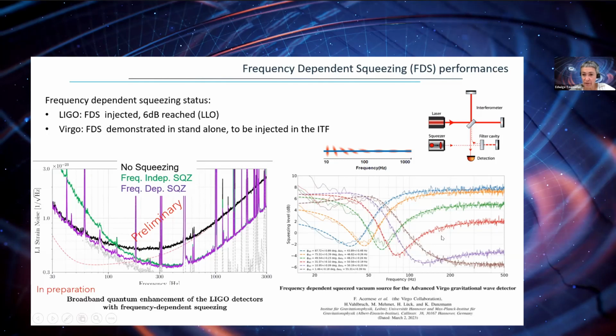In Virgo, we have demonstrated also about 6 dB of squeezing standalone, which means before injection inside the interferometer, and we still need to increase it. On this curve, the performance is shown by the envelope of all these curves, which shows you the level of squeezing which can be injected, and these results have been published also. So that's it for the frequency dependent squeezing, which is a big success.